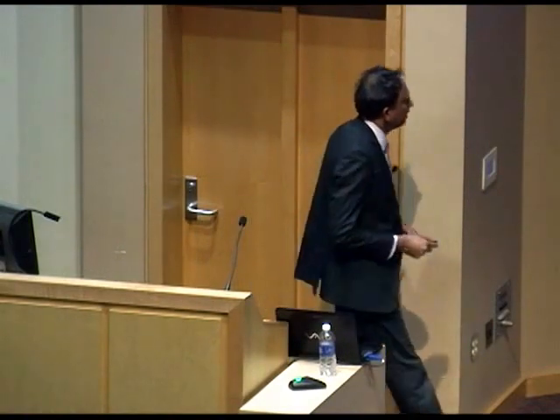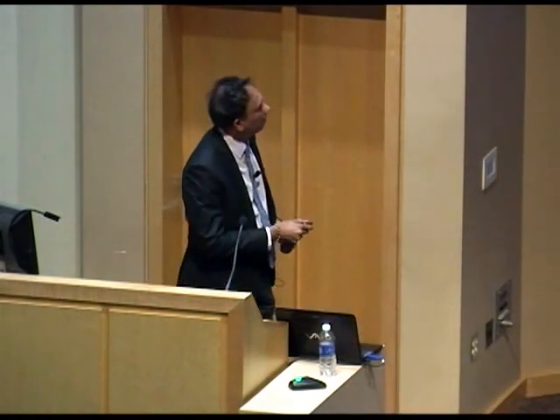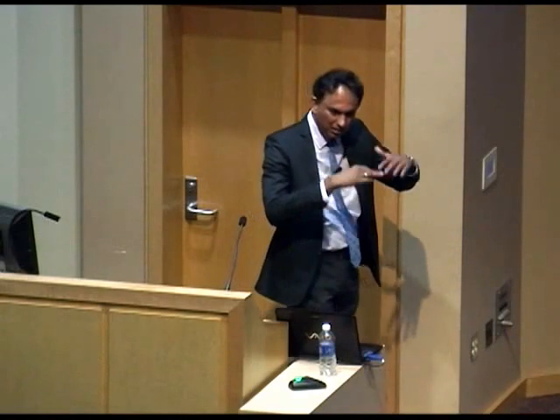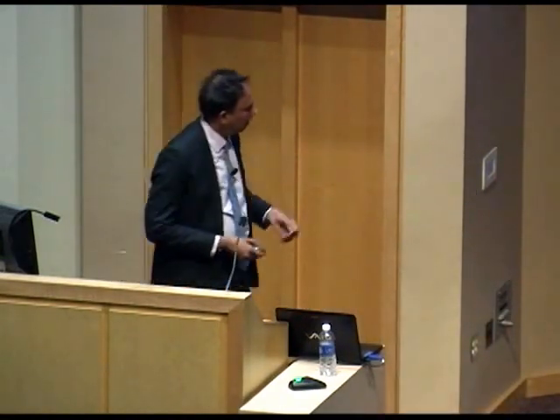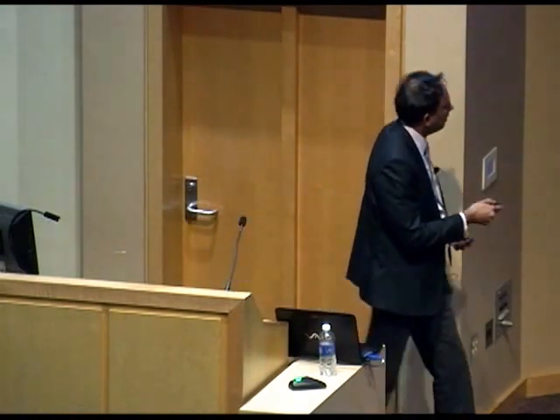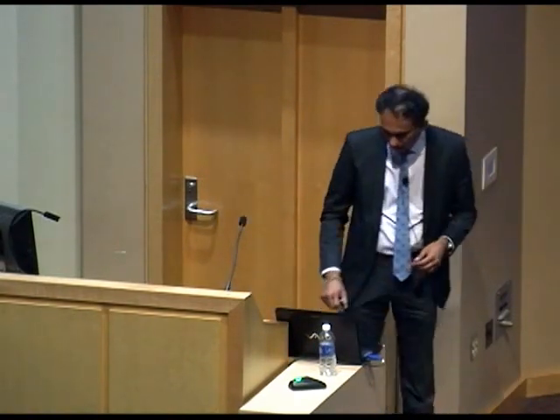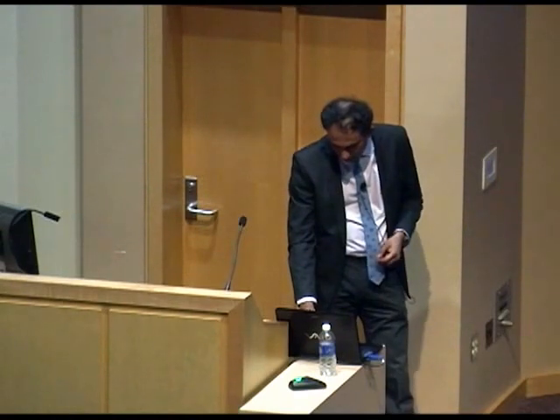Now, that reasonably good arrangement of nanostructures is also very interesting. From a mechanical point of view, we have done a lot of work, for example, looking at the mechanical behavior of these reasonably aligned structures. Now, they are very compliant material. Obviously, graphite has a very low compression modulus in the axis along the plane. So if you make a nanotube, they're also pretty compliant elastically. These are some experiments where we have shown that you can compress these to large strains for a large number of cycles, and it is really quite robust. You don't have much fatigue, although there is some energy absorption because of the viscoelastic nature of that particular aggregate. But nevertheless, these could be dynamically stable structures that could be of interest.